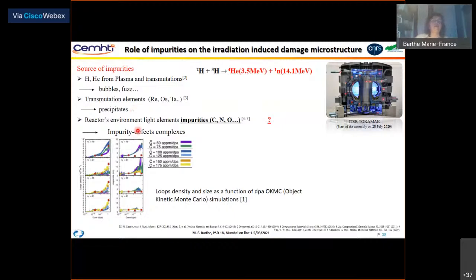And there are also some light elements, such as carbon, nitrogen, oxygen, which come from the reactor environment and are also impurities in the virgin material. It has been shown that various impurity-defect complexes can be created. Here you can see some results of OKMC simulations with different concentrations of carbon, and the formation, that means loop density and the size of these loops as a function of damage dose and increasing concentration of carbon. So there is some strong interaction between carbon and loops.